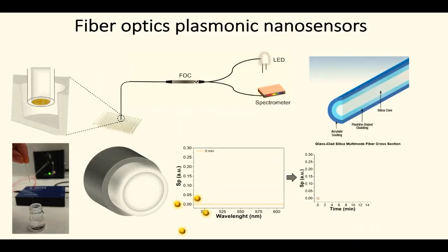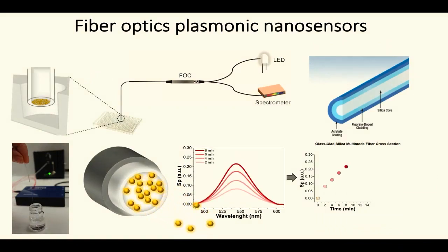So the idea was, can we actually functionalize the glass fiber tip with gold nanoparticles so that we can measure the optical properties of gold nanoparticles? And that's what we did. So the idea was, if we are able to coat the tip of glass optical fibers with gold nanoparticles, perhaps we can see the plasmon peak of the gold nanoparticles and then study their properties.